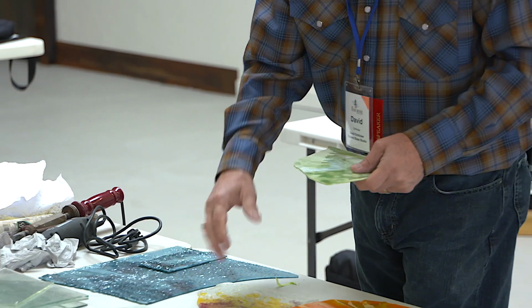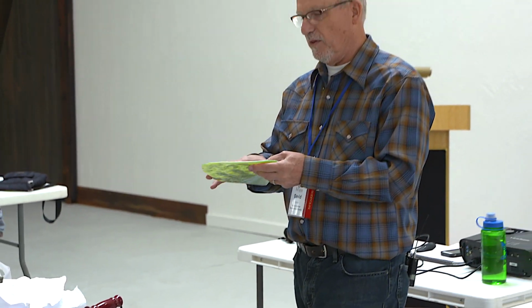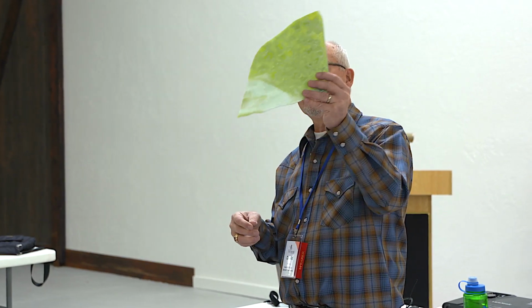So when you roll the sheet out and it starts to shrink and cool on the steel table, the part of the sheet that's touching the table the longest chills the fastest. The part that arches up and gets airborne stays hotter longer, and the colors get to grow in it longer. So that's one of the ways that this glass can be modeled, is just the way it's rolled out and the way it kind of shrinks on the table as it cools. The colors grow in these ring mottle.